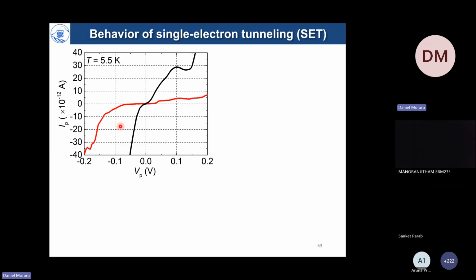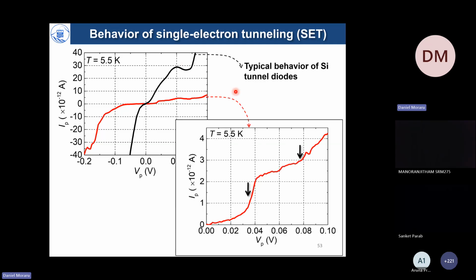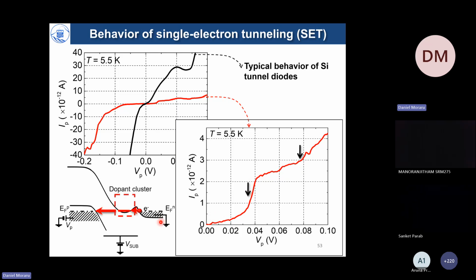So he measured many, many devices, and some of them were behaving as regular Esaki diodes. This is the black curve. Half of the devices behaved like that. Half of the devices, however, behaved with a different, peculiar behavior. They showed very low current at low bias and then a step-like structure of the current, which is also similar to a sort of staircase. Now, we understood that this could arise from the presence of a dopant cluster working in a single electron tunneling mode, but we needed to demonstrate this kind of operation.